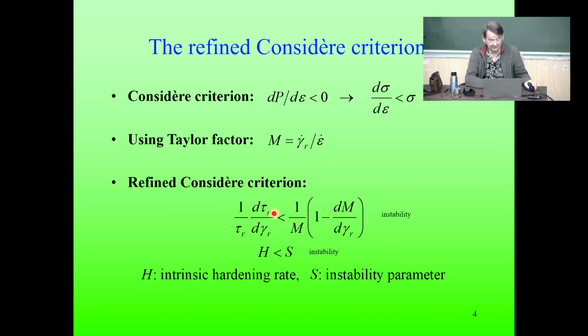And then here one can distinguish two sides. This is a kind of intrinsic hardening, normalized hardening rate, because this is the hardening rate using the resolved shear stress on the slip system. And this is the stress level in the slip system. So this is hardening rate. Let's call it capital H. And on the other side, there is a kind of geometrical parameter, because M is the ratio of these two strains. It's kind of geometrical quantity without a dimension. And so this formula appears on the other side. This we call instability parameter.